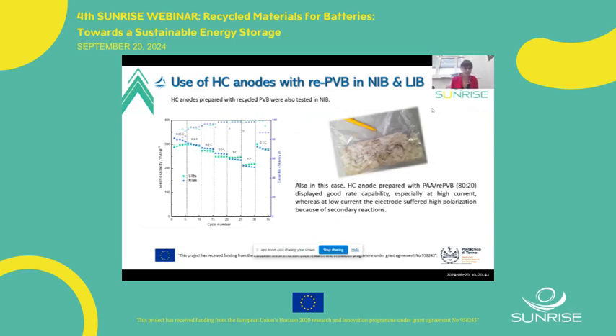As we show, for lithium-ion batteries it's the green, and for sodium-ion batteries we show it with blue. We can see that both electrodes show very good specific capacity, high specific capacity, and good rate performance from low C rate to high C rate.